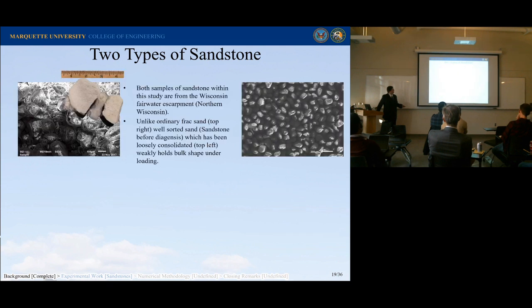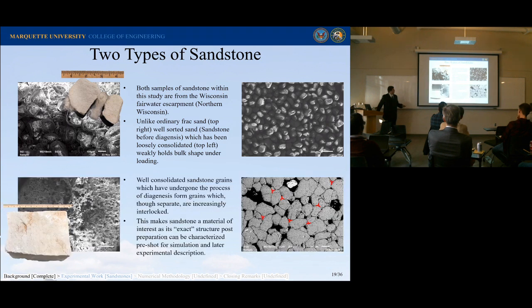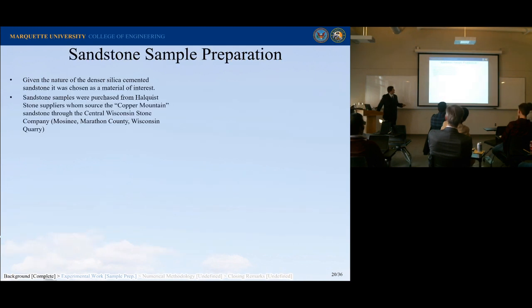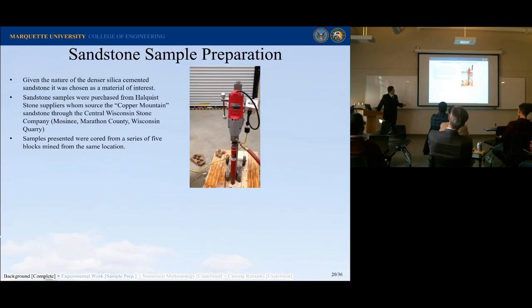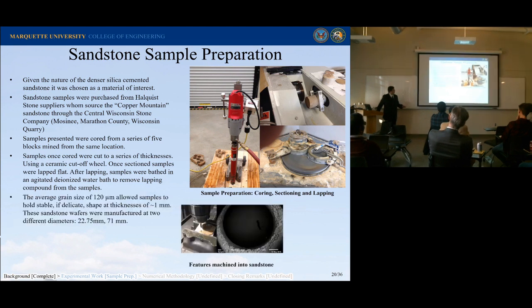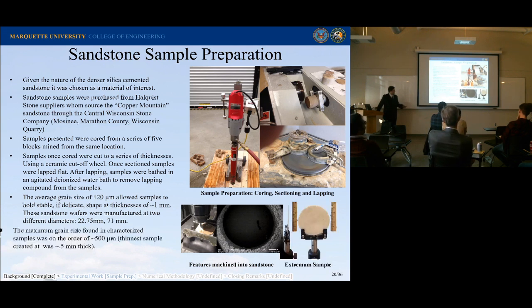So I initially looked at two different types of sandstone. I had this loosely consolidated sandstone, which was really hard to work with. It hadn't really undergone diagenesis and it falls straight apart. And then I have this well-consolidated stuff, which is much closer together, so I can machine it, which is awesome. To prepare it, I drilled it out, then I lapped and cut it, and then finally I could machine properties into the sandstone. This average grain size allowed me to cut samples as thin as 0.5 millimeters, which was interesting because my largest grain size was 500 micrometers. I think there might be a correlation there.